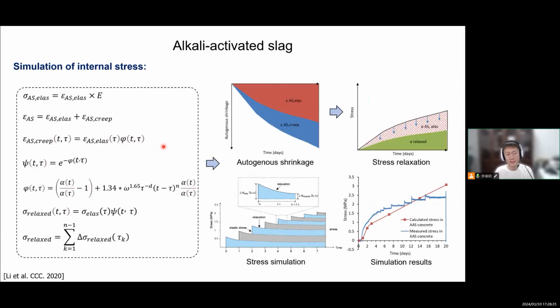The relaxation, we simulated it from the creep coefficient. So we based on the creep coefficient to calculate the relaxation coefficient. And we consider the shrinkage in two parts, elastic and creep, as we said. And then we consider the relaxation. And eventually, the prediction is not that bad. We can more or less simulate the stress evolution in restrained concrete.